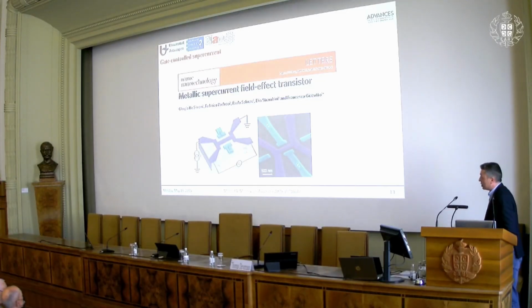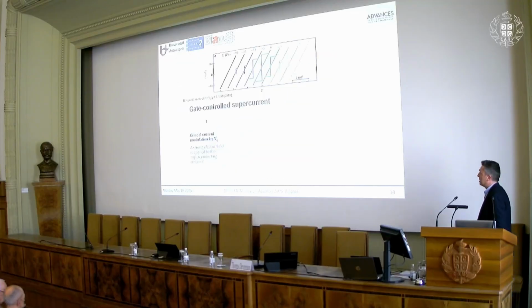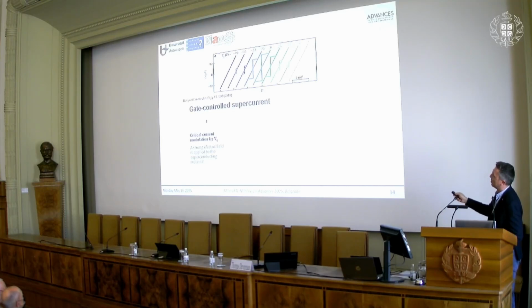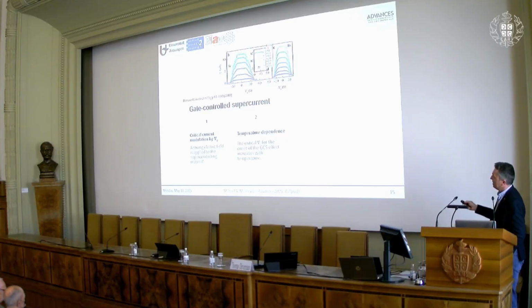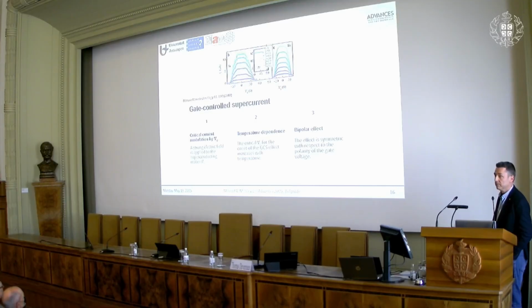Intuition tells us that nothing should change in the superconductor. However, they measured IV characteristics, and they see that the IV characteristics depend on the applied gate voltage, which is right here. So there is a strong effect of a gate on a superconductor, in fact. It is temperature dependent. This is the critical current, the onset of resistance, as a function of gate voltage, and you see that there is a flat region up to which there is no effect of the gate, and then beyond some critical gate voltage, there is suppression of the critical current. It's a bipolar effect, perfectly symmetric with respect to positive and negative gating.